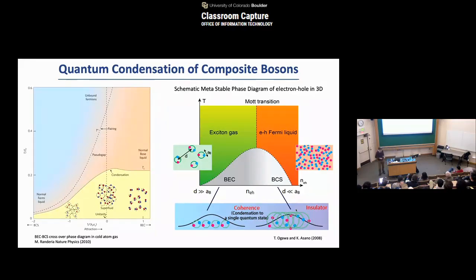And experimentally, people did see this Mott transition happen in semiconductor systems. Whether this is a true phase transition or a crossover depends on whether I can call it a phase, because it's all excited states. So, with finite temperature and finite lifetime, this can be a bit arguable, but it is expected, and experimental evidence has been seen at least in the Mott transition range. The trouble here, again, is the fight with a finite lifetime.